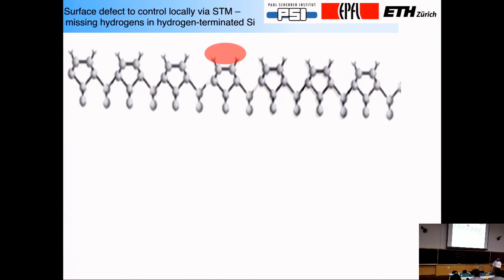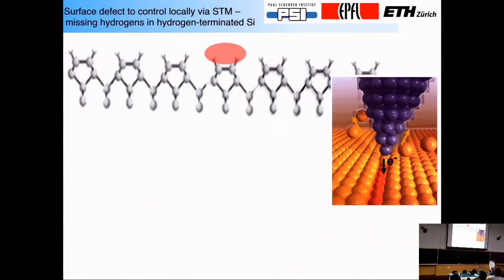Now, let's just look at two of these hydrogen atoms. So one of these hydrogen atoms. If, for some reason, you were able to remove one of these hydrogen atoms, you might actually find that you then had a spare electron there. And in fact, that hydrogen vacancy is then very much analogous to the phosphorus atom with a spare electron in the bulk of silicon. And so what one can do is do model experiments on the surface of silicon, simply using this expedient of removing individual hydrogen atoms to reveal essentially these dangling bonds.